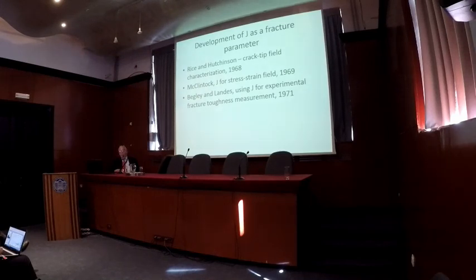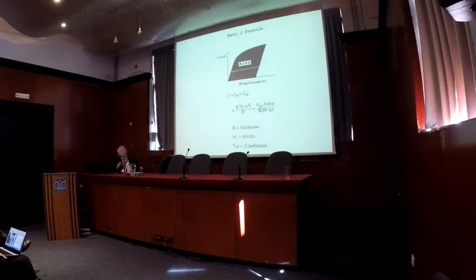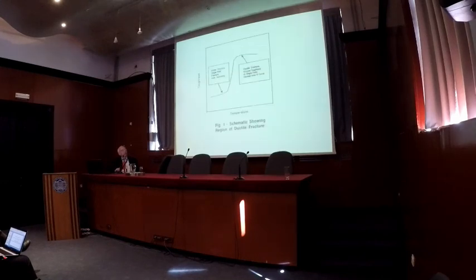Some of the people involved in this: Rice and Hutchinson did a lot of crack tip analysis back in the late 1960s and early 70s, and they are professors at Harvard. And Frank McClintock, professor at MIT, did the stress strain analysis, and then my colleague Jim Begley and myself did experimental work looking at using J for a fracture parameter. The J as a fracture parameter can be represented in this way. An elastic term, which is really the Griffith G term that I showed you earlier today, is the J elastic. The J plastic is related to area under a load displacement curve. And there's a coefficient eta, and B is thickness of the body, W minus a, W is planar width, and a is crack length. So that's that.